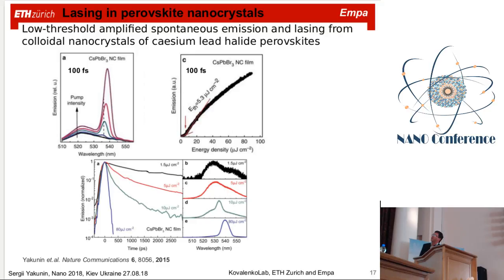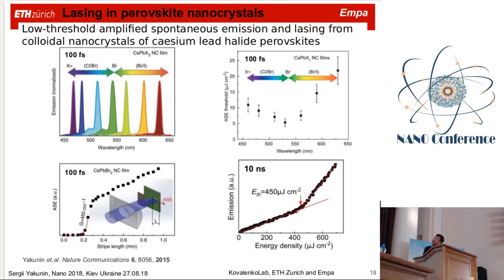And here in a thin film of perovskite nanocrystals, where the thickness is enough to make a kind of waveguide geometry, we see this very narrow, tiny spectral feature with very low threshold, where we also see the effect of drastic acceleration of the lifetime when we slightly increase pump intensity. So these are all the necessary proofs that you have optical gain. And we also demonstrated that these optical gain effects can be tuned through the whole visible range.